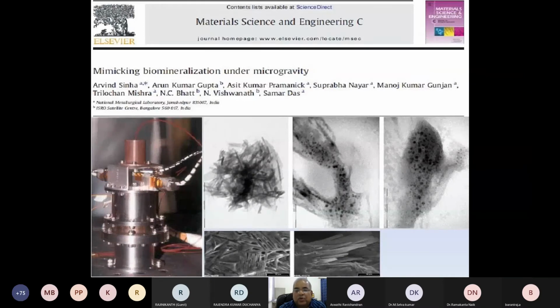When we carried out the electron microscopy of the two samples, one carried out under microgravity in space, and one carried out in our lab, we found that in our lab we synthesized rods of say 100 nanometer in size. But in microgravity, the TEM study showed hydroxyapatite was 3 to 5 nanometer. Right? An order of magnitude reduction in size. There is a lot of microgravity work on crystallization, which confirms that under microgravity you will have homogeneous nucleation of large size crystals, whereas we have got the otherwise result. We have got an order of magnitude reduction, and this indicates the problem that most of the astronauts faced after they come back on the Earth.